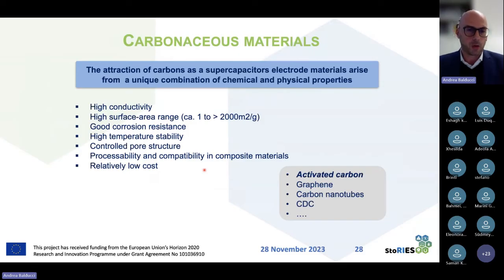And which material can be used to do this? There are, of course, a number of materials that can be realized in a pore, that are porous, but let's say the materials mainly used for supercapacitors are carbon-based materials. Why? Because carbon materials are typically cheap. They can be very easily processed. They can have high conductivity, and they can be realized with extremely high surface area, higher than 2,000 or even more square meters per gram.